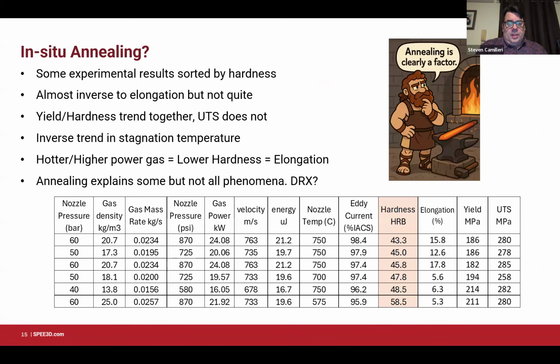Okay, here's some fairly detailed results on the high pressure cold spray. So I've included these really so people can go away and have a bit of a play. I've tried to include some interesting numbers in the columns. For example, I've calculated the effective power in the gas flow, that's column 5, and I've calculated the kinetic energy per particle in microjoules, that's column 7. I haven't been able to do anything significantly useful with these numbers, but nevertheless, they're calculated for interest.